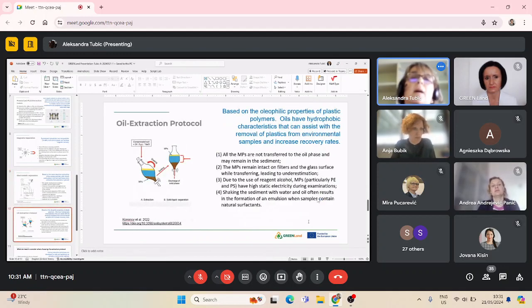And in the end, it's the last one I will show. It's oil extraction protocols, where we use oils to extract the microplastic particles from the samples. It has been determined that it can increase the recovery rates. However, there are also some limitations, like that microplastics are not transferred fully to the oil phase. They can remain intact on the filters or glass surfaces while transferring, so we can underestimate the efficiency of the extraction.